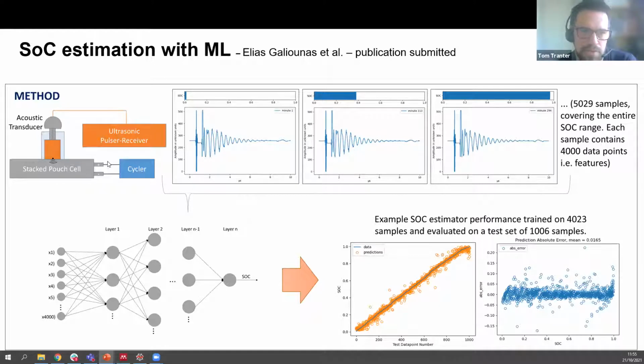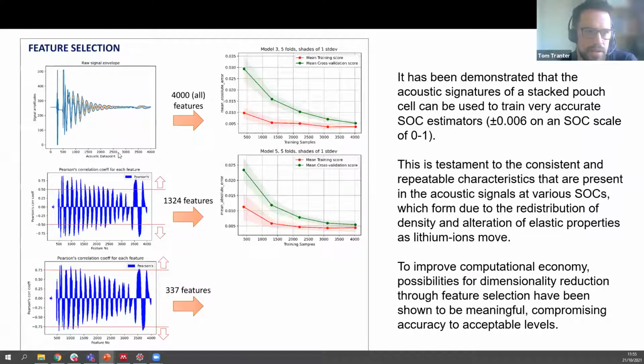We've looked at various different ways to analyze the data with machine learning, different combinations of numbers of layers and things. And also, doing this analysis on the whole feature, we can look at a Pearson's coefficient, which is asking: is this feature correlating well with my output, with my state of charge? So we can see that yes, these particular features are correlating well, they're changing with my final output prediction, and some are not. This one here is actually noise. This is from the transducer before it even hits the cell, and that's not changing at all. So it's a bad correlation with state of charge as it changes over time.